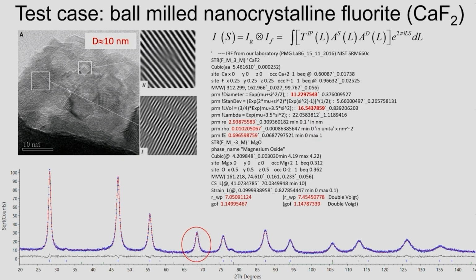Any of you knows? There are two methods, which are not exactly the same. One is you measure the length of all dislocations in a unit volume. And of course, the units will be meters to the minus 2, right? Length divided volume. Another equivalent is you imagine a square meter surface and you count how many dislocations cross it. And then again, it will be number over square meter, meters to the minus 2. And for materials with a lot of dislocations, 10 to the 16 per square meter is a reasonable number, just to give you numbers.